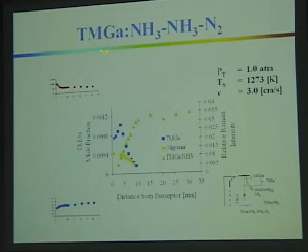We then go on and look, and we intentionally formed this adduct. We mixed ammonia with trimethylgallium, deposited it out in excess in a packed bed, and then flowed just ammonia and nitrogen over that to form a saturated solution of trimethylgallium ammonia adduct. What you see here in green is the concentration we're measuring from the inlet to the surface.